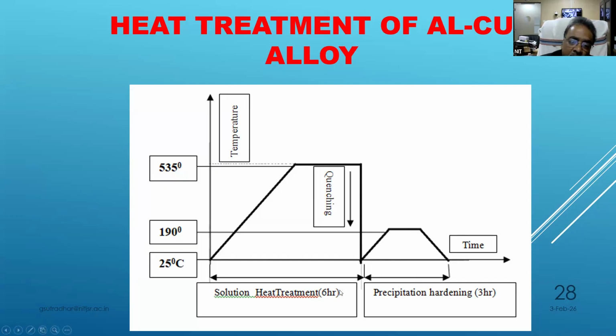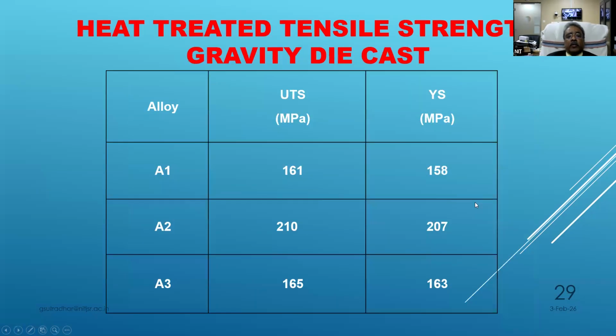These 6 hours are for this particular alloy, but for other alloys like LM25, LM9 or LM11, this may be 8 to 12 hours, and precipitation hardening may be 3 to 5 hours. The soaking is about 1 hour, but it changes depending on the alloy. Now if heat treated, the alloys change again, but this A2 with 8% copper remains giving better results compared to the other two after heat treatment also.